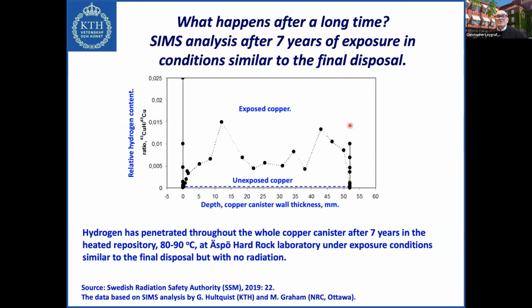But this also then goes to the next question: what happens after a long time? Actually, here are some SIMS analyses after 7 years of exposure in conditions similar to the final disposal. And these results show the hydrogen results as a function of depth of the copper canister. And what they show is that actually hydrogen penetrates throughout the whole 5 centimeter copper canister thickness after 7 years. This is in the heated repository.